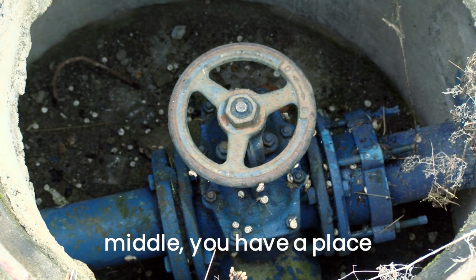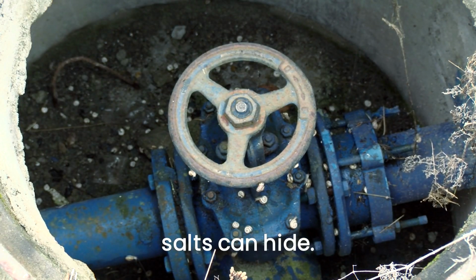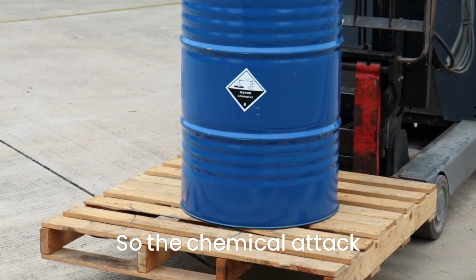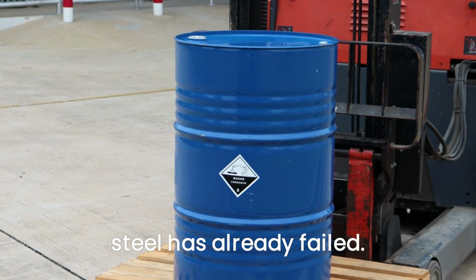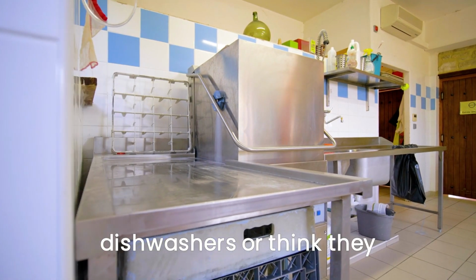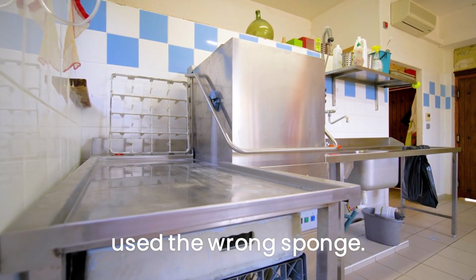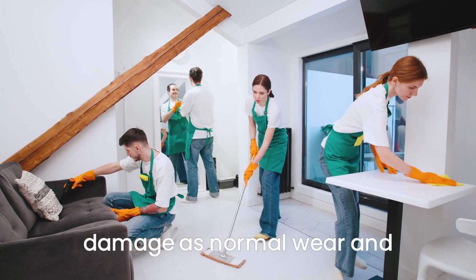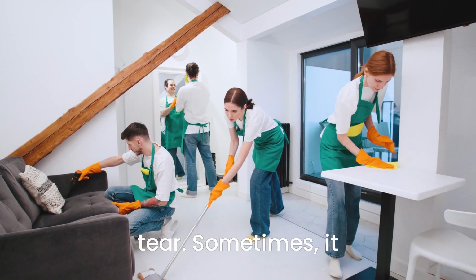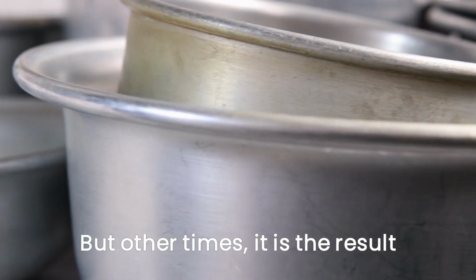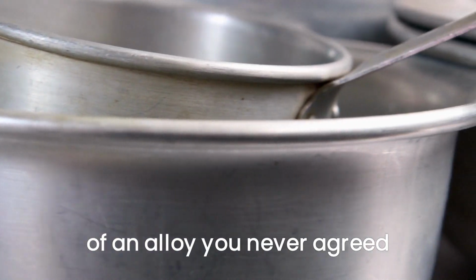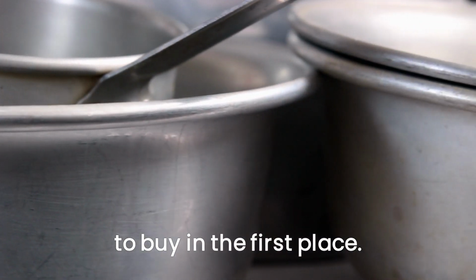Once you have a pit in the metal, you have a place where moisture and salts can hide. So the chemical attack speeds up right where the steel has already failed. People often blame their dishwashers or think they used the wrong sponge, and they just accept the damage as normal wear and tear. Sometimes it really is just wear, but other times it is the result of an alloy you never agreed to buy in the first place.